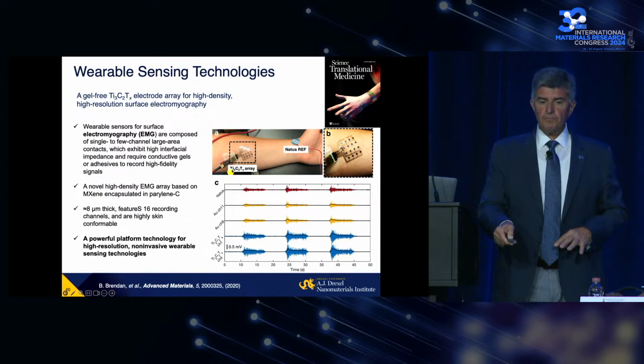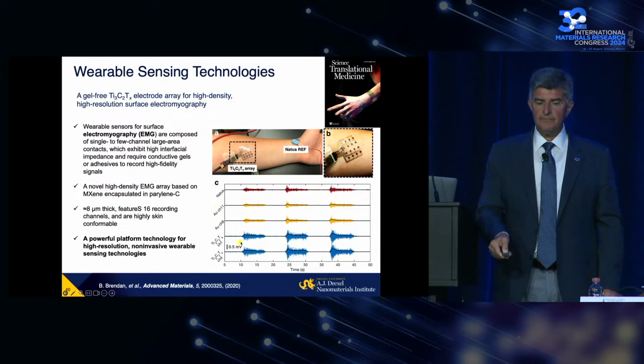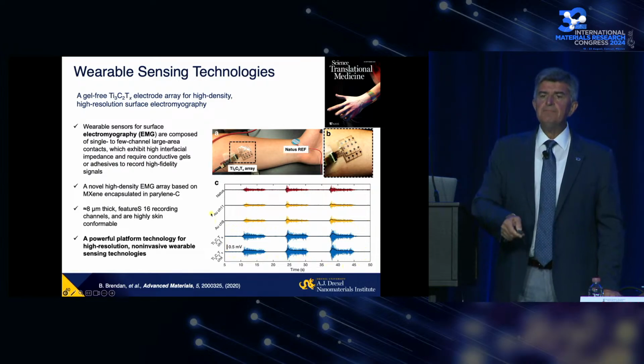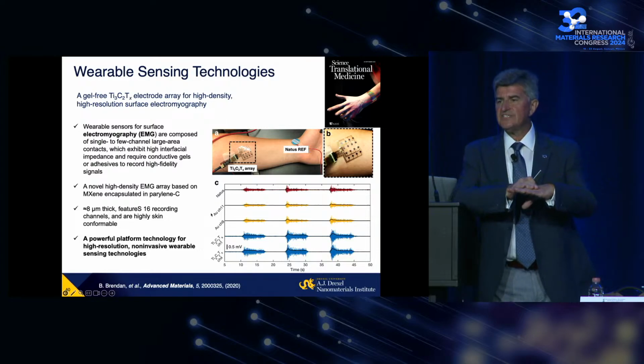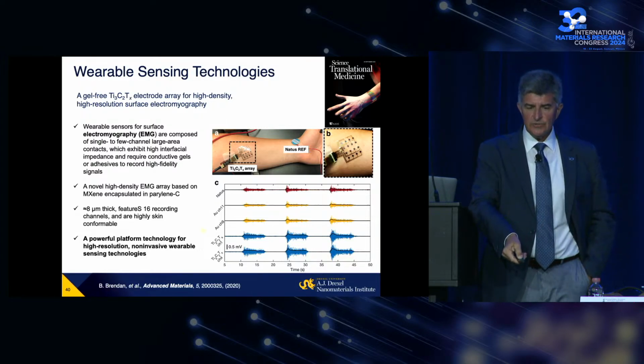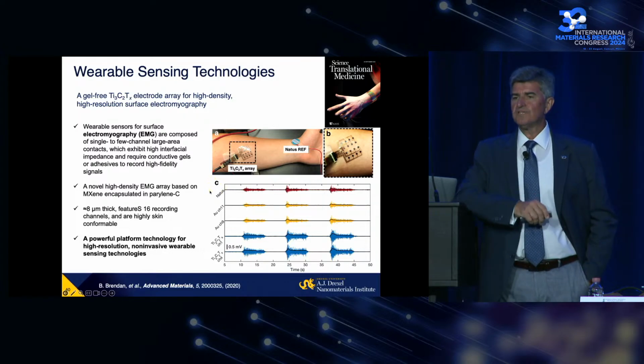Typically gold or platinum is used. Gold and platinum are more conducting than MXene, but MXene, because of its hydrophilic surface, has better impedance with skin, so contact resistance is lower. As a result, you see the signal intensity, this spike intensity, higher compared to gold sensors of the same shape or commercial gold sensors.